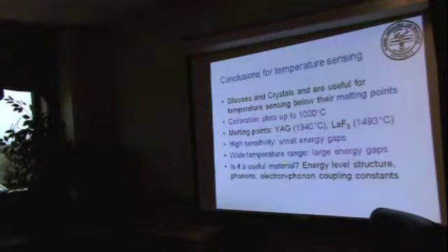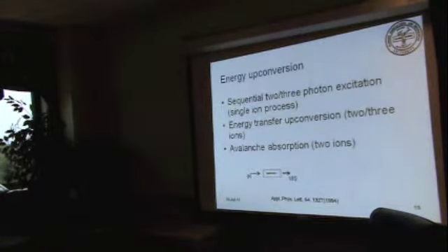Whether a given material is useful or not depends on the energy level structure, the phonon structure, and the electron-phonon coupling constant, because these things decide how fast the non-radiative relaxation is going to be. So this is for applications where your conventional techniques fail. You can use this for temperature measurement in corrosive environments. Now I'm going to show another example, energy up-conversion.